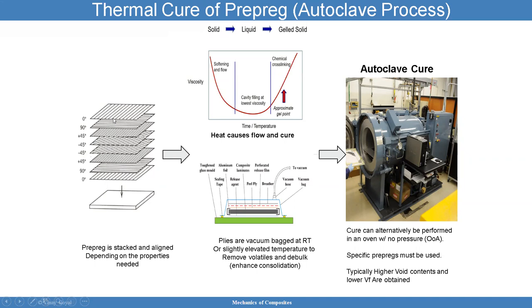So these lamina, which are the prepreg lamina, are then cut, and then you stack them up against this tool, and the prepreg is stacked and aligned depending upon the material properties that you want, which is why we're tailoring these composites. And then I go through the process of going from solid to liquid to gel to solid. That's the process I want to follow. And so you have some amount of softening and flow. The viscosity is fairly high. Then things become liquid, and then you have chemical cross-linking. And here, again, the viscosity will be changing. And here, you're going to have an approximate gel point of some kind.